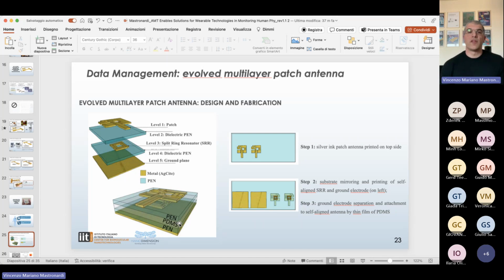So the first step of the fabrication protocol consists in the printing of just the silver ink patch antenna that is printed on one side of the polyethylene naphthalate. Then we keep the same substrate, but we mirror it in order to print the self-aligned split ring resonator that is aligned with the patch antenna, and the ground electrode that is on the free part of the substrate itself. Then we split the ground electrode from the remaining part of the substrate, and we attach the ground electrode and the patch antenna plus the split ring resonator by using the PDMS sticking layer.